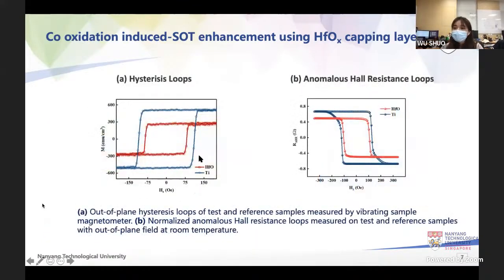After the sample fabrication, firstly, we investigated different magnetic properties of our samples. This is the out-of-plane magnetic hysteresis loop of the thin films at room temperature. You can see the square loop indicates strong PMA, and this figure shows the anomalous Hall resistance. It's clear the HFO sample shows a lower squareness in the AHE. We believe the decreased coercivity and the Ms are closely related to the cobalt oxidation. This will be further verified by the following experiments.